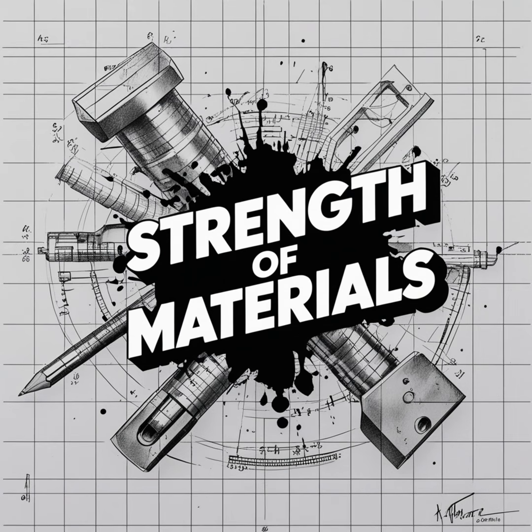And remember, each grain has its atomic lattice oriented in a slightly different direction. Oh, so the grid changes direction. Exactly. When the crack reaches a grain boundary, it can't just slice straight across. The weakest atomic planes in the new grain are pointing in a different direction. The crack has to physically reorient itself to follow the path of least resistance through the new crystal lattice. So the crack is forced to turn. This is what researchers call crystallographic crack path deflection. Exactly. The crack literally zigs and zags. It tilts and twists three-dimensionally as it navigates the maze of crystal boundaries.